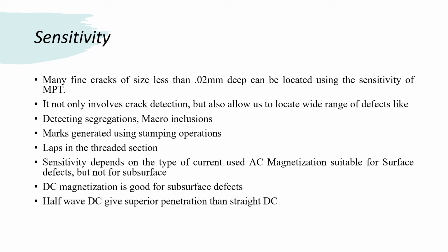A surface scratch which may be as wide at the surface as its depth usually does not produce a magnetic pattern, although it may do so at a high level of magnetization. Because of many variables, it is not possible to establish any exact values for this relationship.